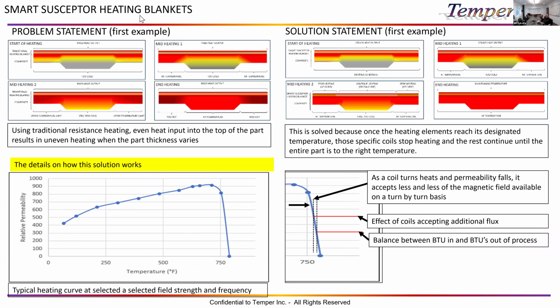So in the case of a traditional heating blanket, for instance, you end up putting a certain amount of heat into, let's say, a part, and I've got a thick area of the part and thin areas of the part. What happens is the heat continues, because in order to get this thick area up to temperature, you've got to continue to heat it, which gives you overheating at the edges. With a smart susceptor heating blanket, it starts to approach its Curie temperature, and we end up with even heating.